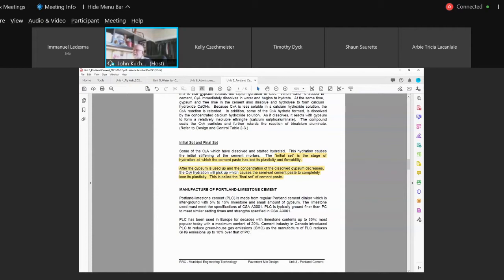Don't worry about the C3A hydration, but after the gypsum is used up and concentrations of the dissolved gypsum decrease, this is what causes the semi-set cement paste to completely lose its plasticity, then that's called final set. So you're going to get an initial set, and then you're going to get final set when you lose that plasticity, and you can walk on it.